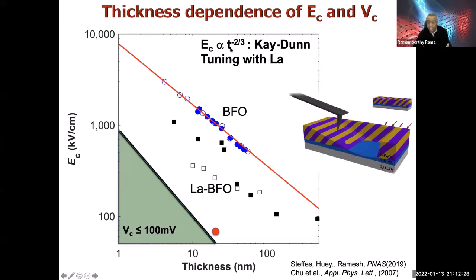It actually scales quite closely to the Kay-Dunn law. The thickness is t, and it scales as t to the power of minus 2/3. And we need to get to this green area. You can see that there are some samples in our collection, the 20 nanometer sample, which is reasonably close. But we still have some work to do in terms of optimizing our materials.